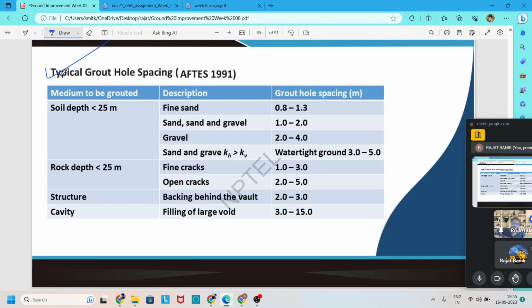One spacing table is given for this grouting, given by AFTES in 1991. It is said that when we improve the soil below 25 meter depth, then for fine sand the spacing should be 0.8 to 1.3 meter. For sand and sandy gravel, it is between 1 to 2 meter. In the same way, for rock depth less than 25 meter, for fine crack the spacing is 1 to 3, and for open crack the spacing is between 2 to 5. Based on this table, we can easily find the spacing for different materials at different depths.